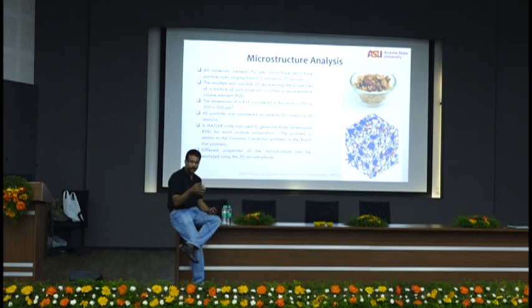Then, once the cube is full, it will pick the next particle according to the proportions you've given, and if it doesn't fit, it will try to rearrange the other particles and fit it. It goes through a recursive algorithm, probably 1 or 2 million steps like that, to come up with a complete packing, and tells you the packing fraction. We consider all particles as spheres for the sake of ease. Angular particles would take a lot of time to model.